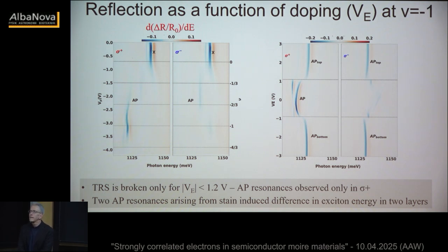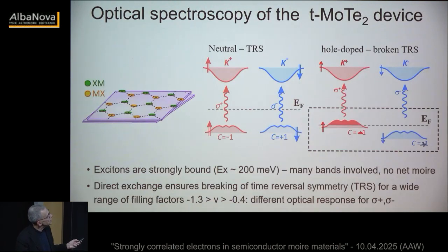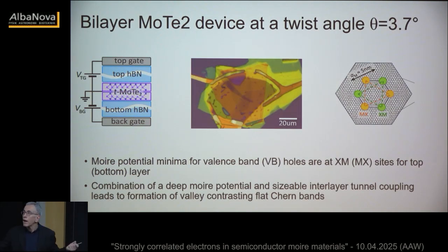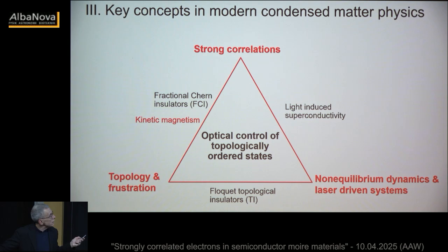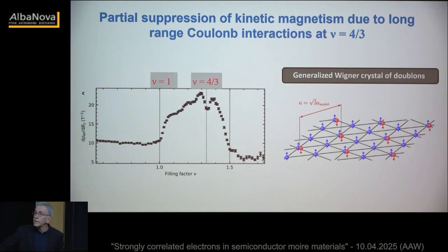Hello. I just want to ask how hard is it to synthesize these kind of samples, because these properties are material based. So how hard? It's not easy. I mean, the last set is twisted molybdenum. We haven't tried it yet because, as I said, Shadon kindly agreed to provide us. Now, with the other sample, this device that we investigated here, we basically made 4 attempts, and 2 of them worked nicely, exhibited the moire lattice structure. So I think that's a relatively low rate for us, so it doesn't speak so well for our abilities, because here it should be higher, but it's never 100%.